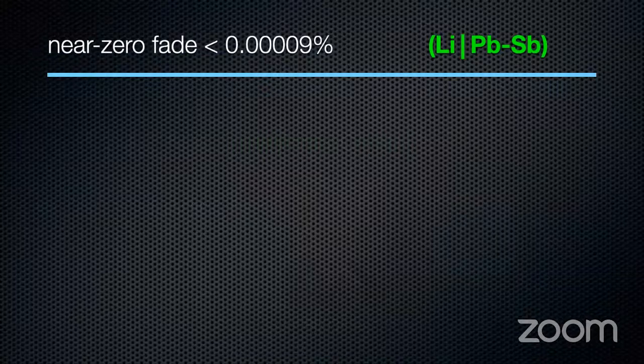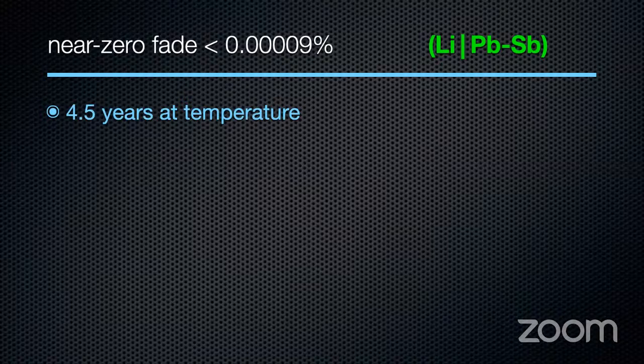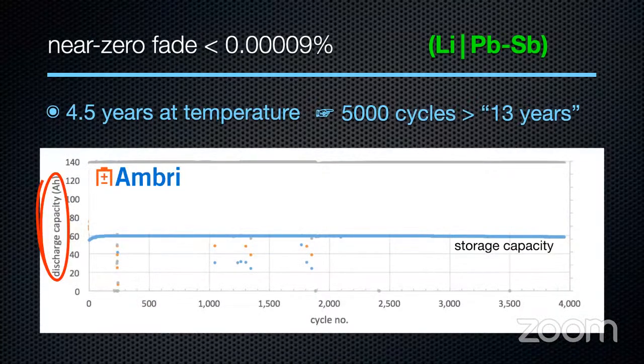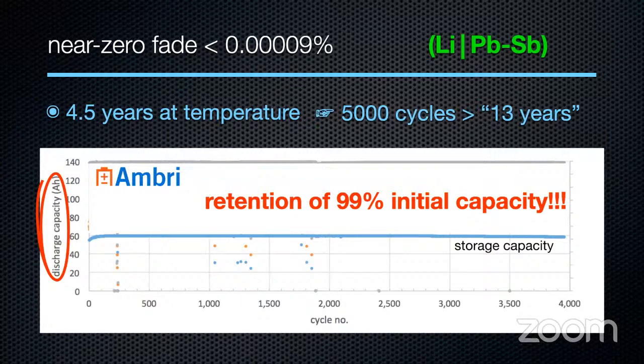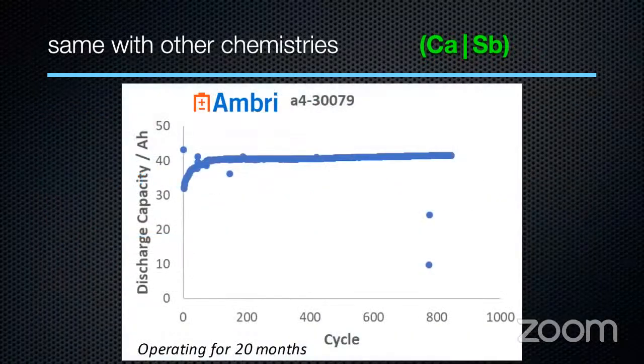All right. So this is when we were working with Ambri, almost 5 years, 5,000 cycles, deep discharge every day would be like 13 years. And look at this is the capacity. This capacity is retaining 99% plus of initial capacity. If I put lithium ion on here, lithium ion would start here and would sink like a stone. By about 2,000 cycles, it would be down to about 70%. Well, if you're down to 70% of nameplate capacity, you can't meet your technological requirements, which means you either have to add new capacity or have it on day one. So that's good. And this is now with calcium antimony, same thing. In fact, if you look carefully at this line, my eye tells me it's actually getting better with cycling.